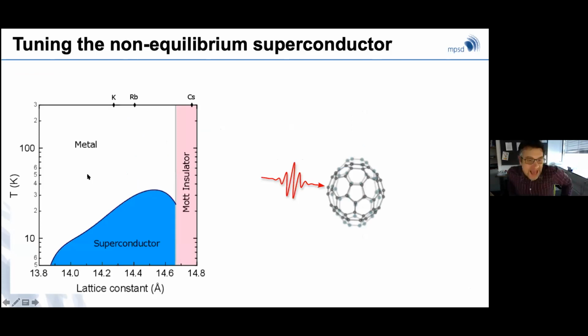So this brings me to the last part of the talk, which has to do with finding ways to A, tune these properties of the light-induced superconductor, and B, it's a step toward understanding whether the features of this light-induced long-lived zero resistance state has other characteristics of the superconducting state. So one of the important points that I will discuss here is how if you either change the alkali atom or you apply pressure, as you reduce the lattice constant, the superconducting transition temperature, at least for lattice constants that are smaller than the peak of the dome, tends to reduce.